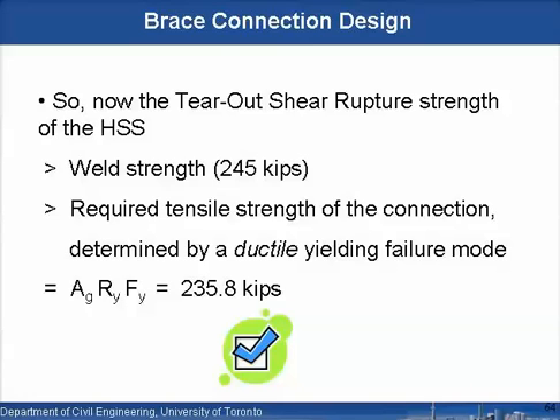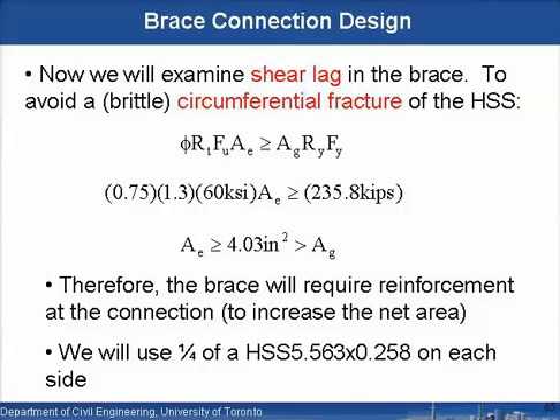So what we've essentially done now is made sure that the tear-out strength or rupture strength of the hollow structural section is greater than the weld strength, which is 245 kips if we were to calculate it based on those calculations, and that in turn is greater than the required tensile strength of the connection determined by a ductile yielding failure mode, which is the AgRyFy, 235.8 kips. So the lowest governing force is actually a ductile failure mode of AgRyFy. All the other connection parameters have a strength that exceeds this. So that's what we're aiming for.